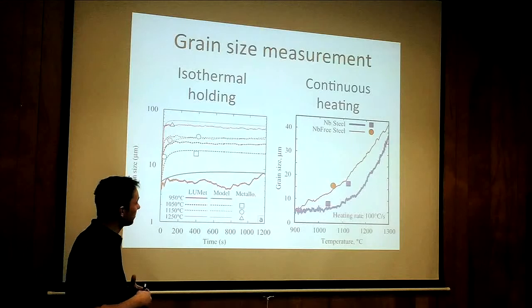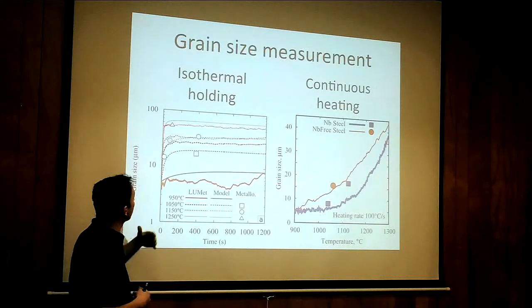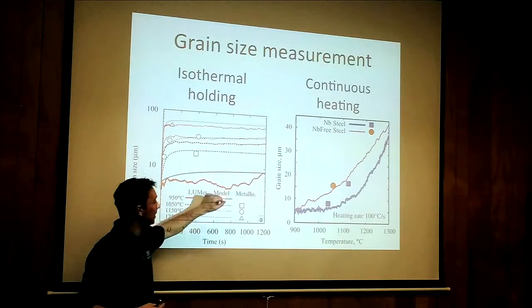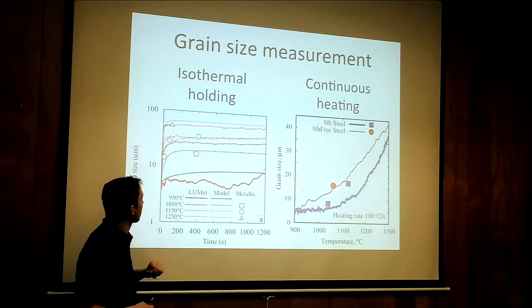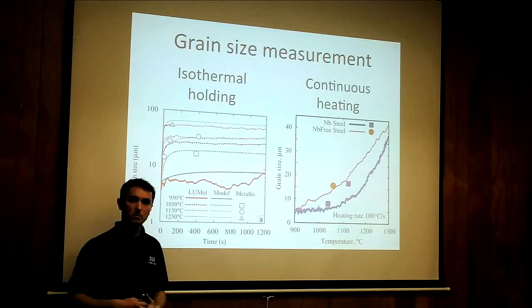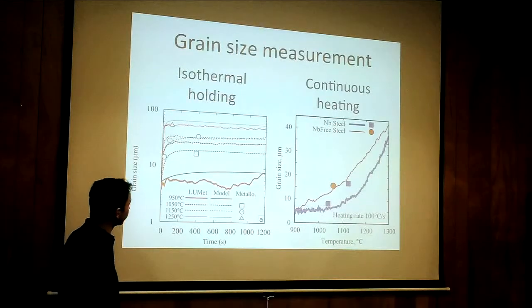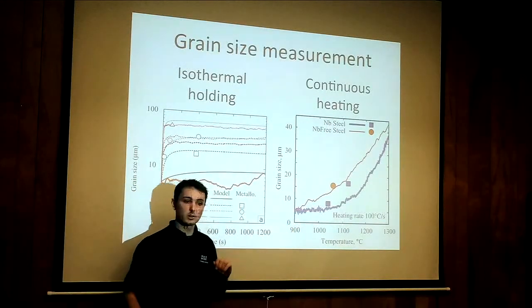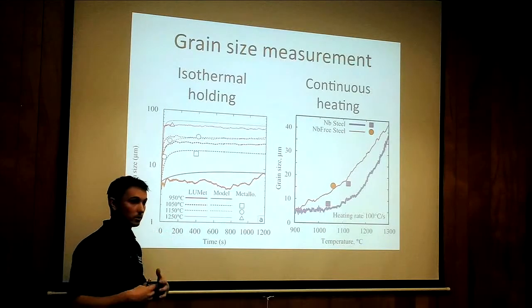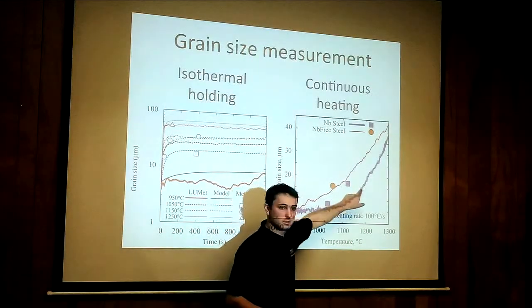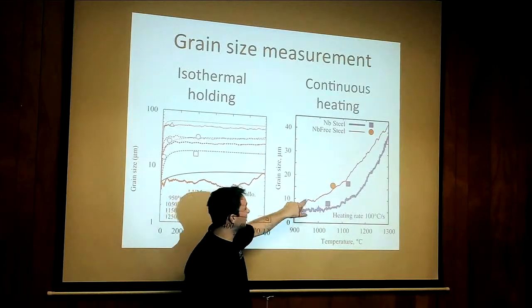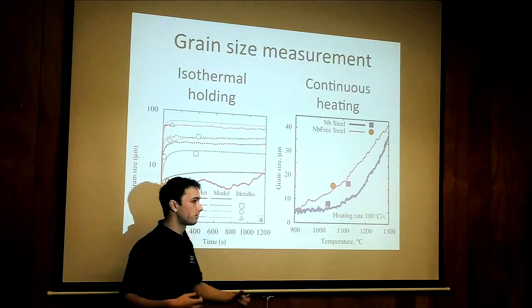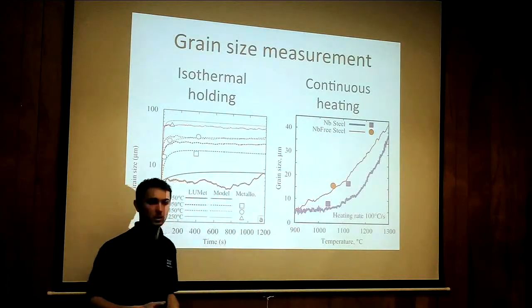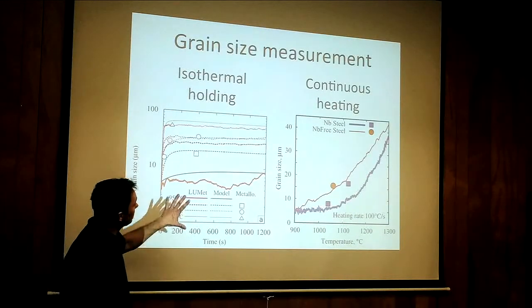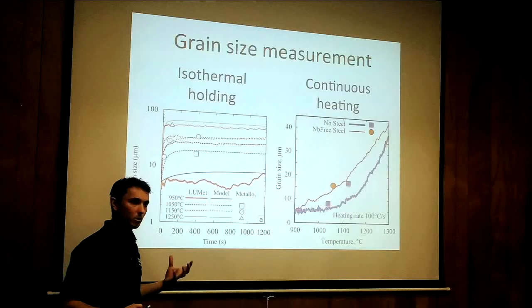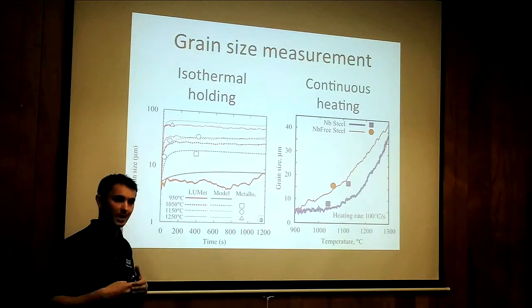So thanks to Lumet, it's now possible to acquire the change in this grain size during isothermal holding here, where the red curves are the values of grain size measured with Lumet, and those points here, which relate very well with Lumet measurements, are verifications of those grain sizes. During continuous heating here, this is another example where we can discriminate between a steel that contains some precipitate, in which the growth of those grains is very slow, it's the blue curve here, and a steel which does not contain precipitate, in which those grains grow fairly rapidly here. So it tells about the sensitivity of such a device. What is important to remember is that this grain size measurement is made from the measurement of the attenuation.